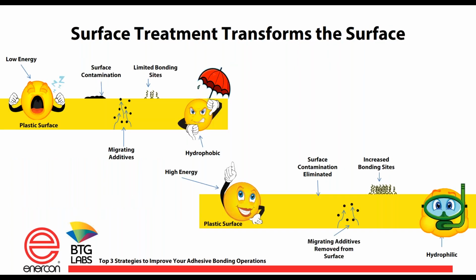So now here's what we started with. If we have a bad surface, maybe a plastic surface, it's going to have a low surface energy. There may be contamination on the surface that hasn't been cleaned off. If you're dealing with polymers, you may have additives in there that are migrating to the surface. Flame retardants come to mind. All of these things give you limited bonding sites, and we call this a hydrophobic surface. This would be a similar surface to a waxed automobile or a rain-x'd windshield. In these cases, the water just beads up and rolls off. And that shows that we have a very low surface energy.